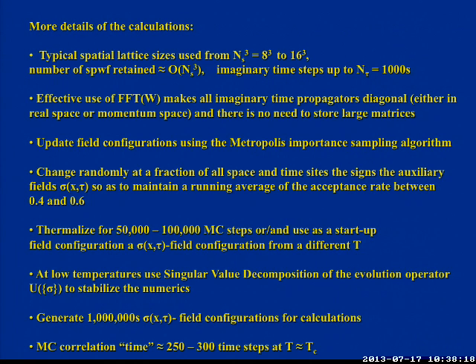Now, a little bit more details about this. Typical lattice sizes we calculate are 8 to 16 cubed. The number of single particle wave functions retained is of the order of this number cubed. The number of time steps is basically thousands. So if you put it all together, it's much larger than lattice QCD, for example. You see the spaces. We use FFT because we work in both momentum and coordinate space. So this allows us to simply get rid of matrices and so on. Calculation is very fast. We update the field configuration using Metropolis.